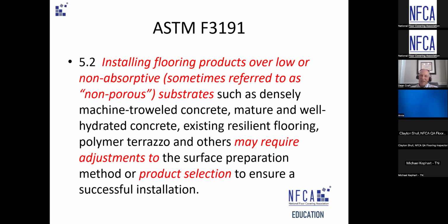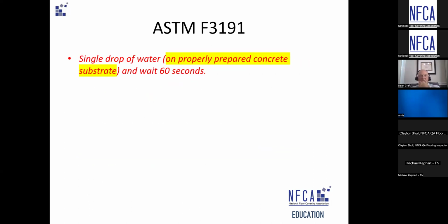But the reason this ASTM keeps bringing in non-porous is that so much flooring literature says suitable for porous or non-porous. Those words were so entrenched in so much literature, we brought it over to the standard just to keep it on there. The standard is about as easy as possible: a drop of water, wait 60 seconds.